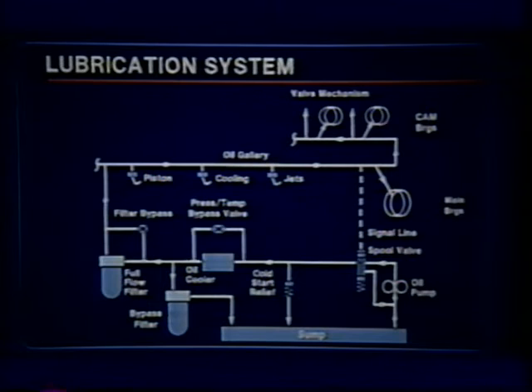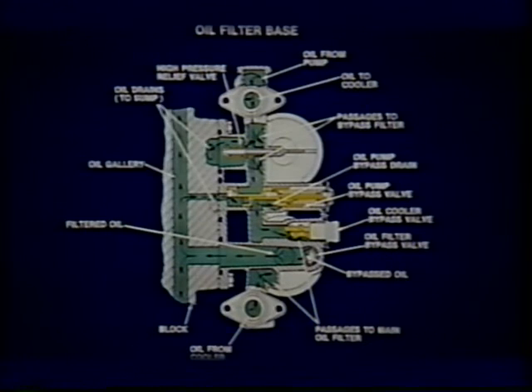The lubricating schematic includes these features: a thermostatically controlled oil cooler bypass valve to maintain the optimum 110 degrees Celsius oil temperature for longer component life, a high-pressure relief valve located in the filter base to protect filters and other components during cold starts. A damaged filter could allow contaminants into the lubrication system, damaging internal engine components. The relief valve opens at 101 psi.